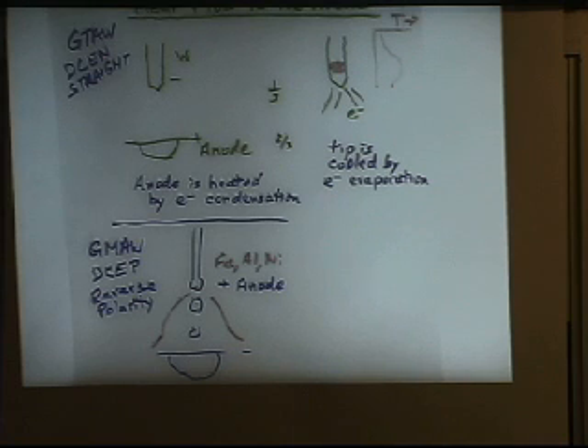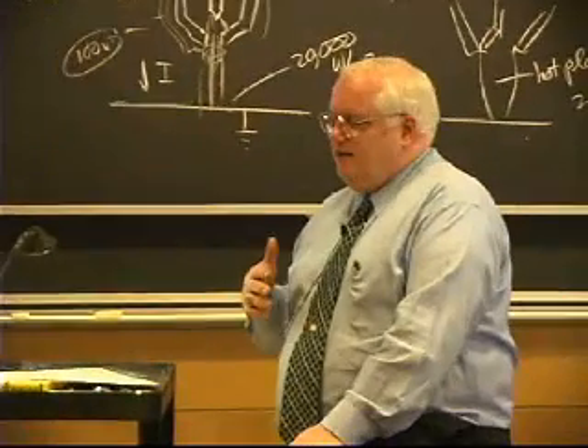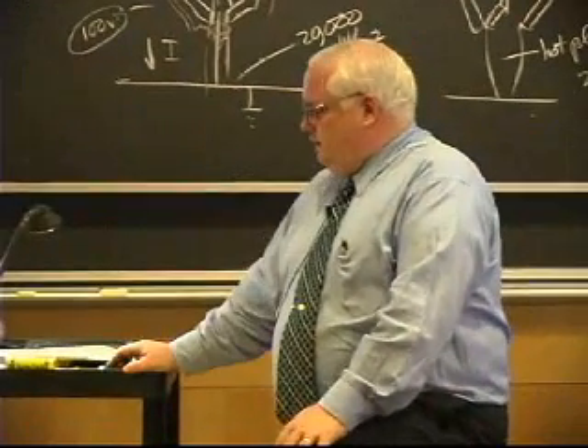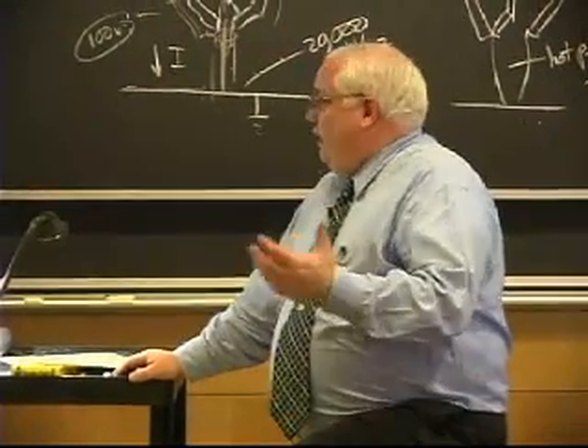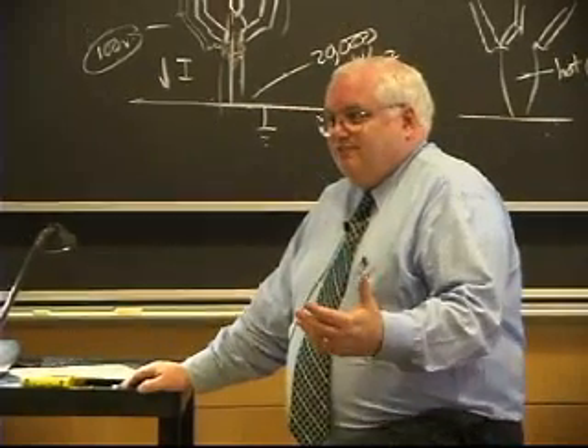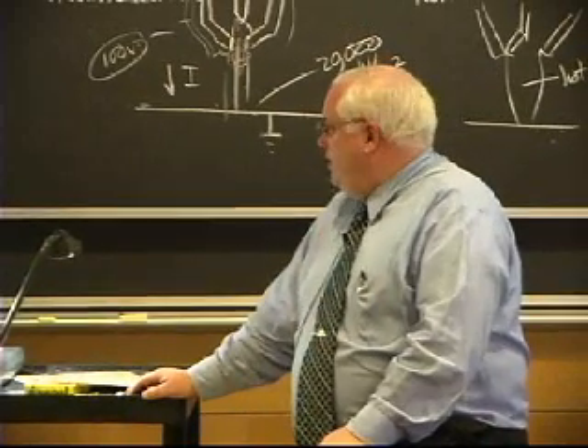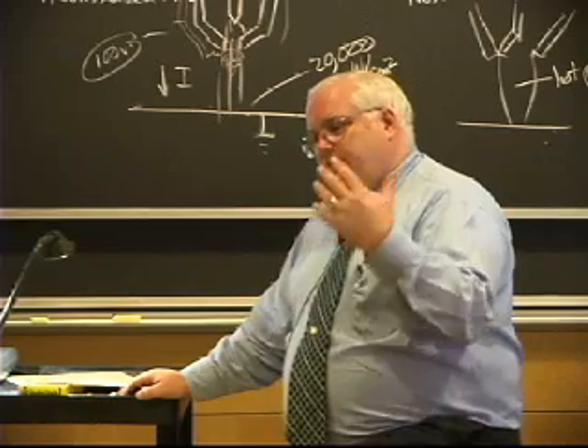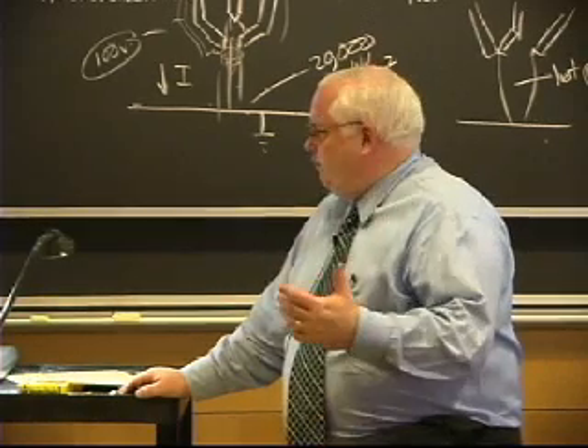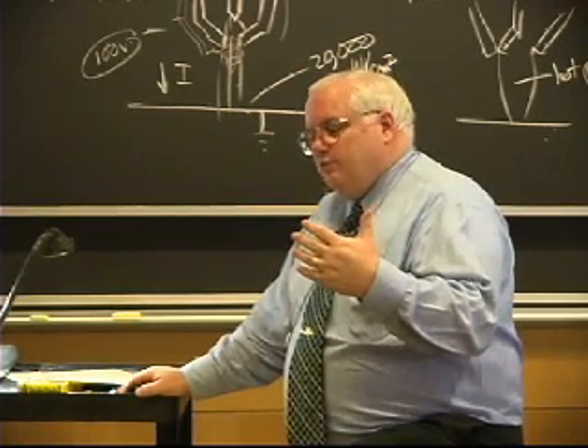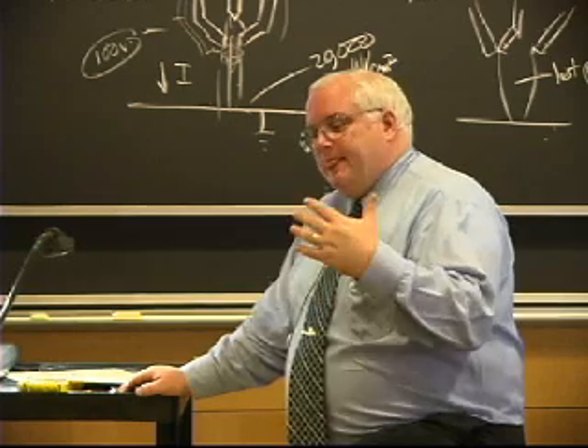Well, it turns out when I'm welding, particularly aluminum or magnesium, and I really don't want to weld magnesium, it can be welded, but magnesium is very, very susceptible to stress corrosion cracking, and all you need is some stress on the magnesium, and it will just crack like mad. And welding in general creates residual stresses in heavy plate and heavy section. I used to have a magnesium hand truck. Actually, I guess I still have one at home. I had two at home. Someone borrowed one on the no return plan.